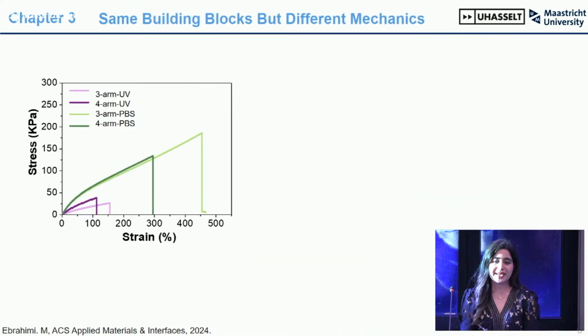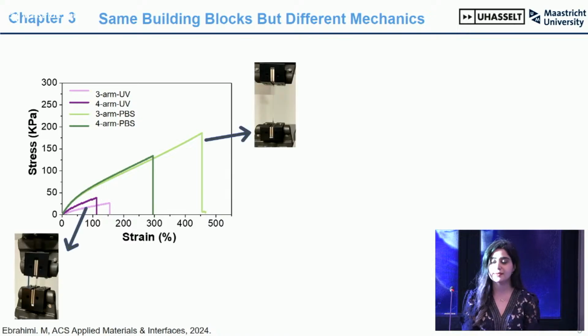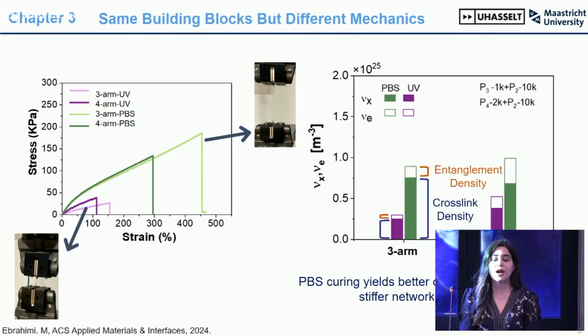I characterized the mechanical properties of these hydrogels, and as you can see, PBS-cured hydrogels, the green curves, had higher elastic modulus and also greater extensibility compared to the UV-cured ones. Quantification of entanglement density and crosslink densities obtained from data modeling also confirm that PBS curing yields better cross-linking efficiency and a stiffer network than UV curing. But why?